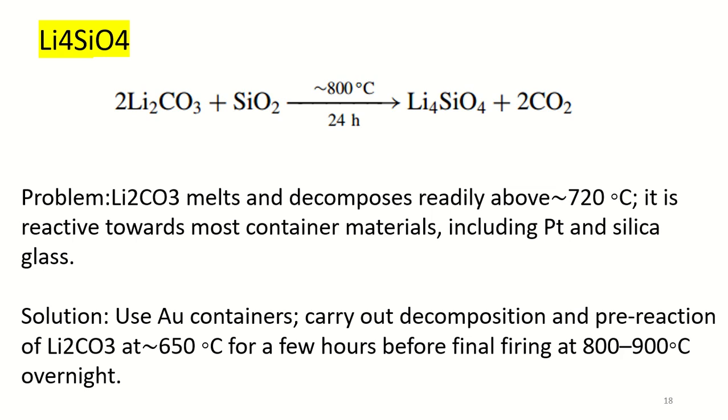So instead of using silica glass or platinum containers, it is better to use a gold container, which is more unreactive towards lithium carbonate. Moreover, the pre-reaction of lithium carbonate should be done below 720 degrees Celsius, because this is the temperature at which it readily decomposes.